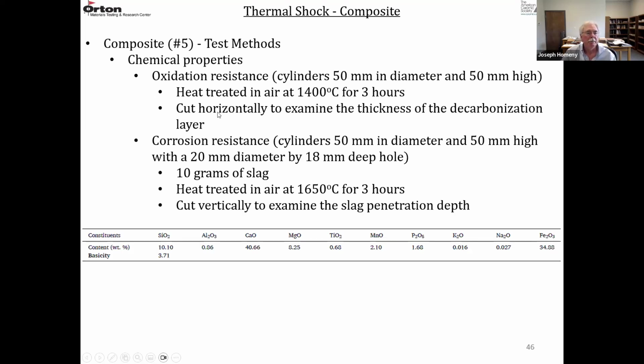They also looked at oxidation resistance and corrosion resistance. Again, carbon matrix composites are designed for good thermal shock resistance and good corrosion resistance. Oxidation resistance is always an issue. Once you oxidize the carbon, you no longer have a composite. So they measured the oxidation resistance on these cylinders, again 50 millimeters in diameter, 50 millimeters high, and they used the same size cylinder to measure the corrosion resistance. This is a qualitative measurement they did.